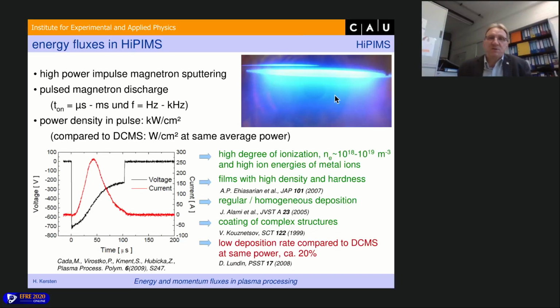You know, the difference between HiPIMS and DC magnetron sputtering is that you have the whole discharge power in a very short pulse of the discharge. That means you have very high power density at the magnetron target for a short time. And so you have a lot of sputtering of the metallic species, and also a very high degree of ionization of these sputtered species. So the ionization of the sputtered material is much, much higher than in DC sputtering.